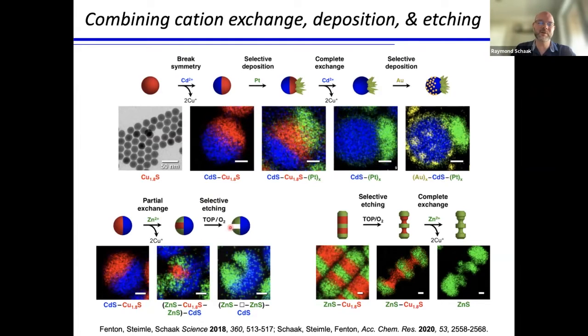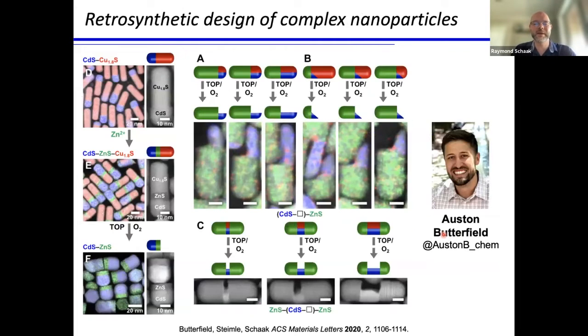Or there's also really nice and powerful etching chemistry that Richard Robinson's group showed really nicely, where you can etch out selectively the copper sulfide. So any regions that we have that have remaining copper sulfide, we can etch out to make even crazier types of nanoparticles with void spaces and intricate sculpting. So there's a whole other level that can be achieved by merging this with other techniques.